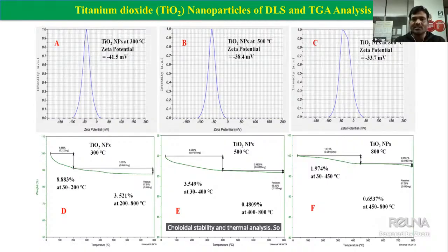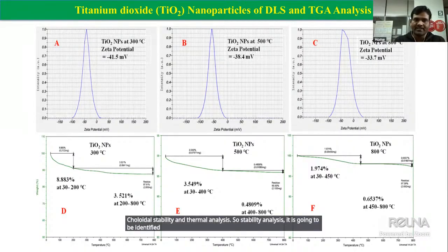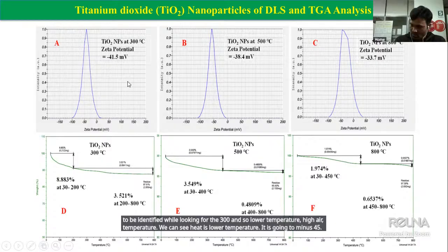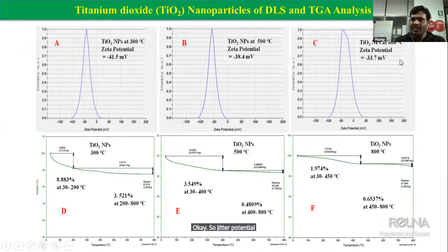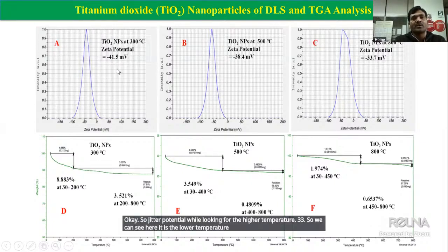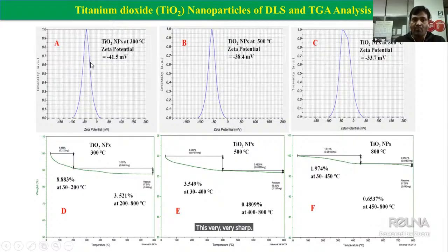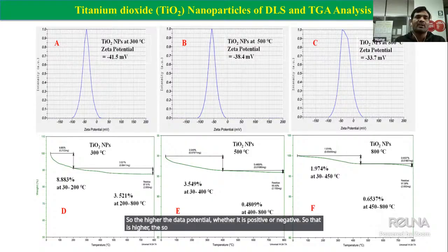So the stability analysis is identified for the lower temperature and the higher temperature samples. We can see here the lower temperature is minus 45, okay, the zeta potential. While the higher temperature is 33. So we can see the lower temperature sample has more stability of the nanomaterial. Why? Because it has a very sharp peak. The sharp peak indicates higher stability of the material. So that means the higher the zeta potential, whether positive or negative, the higher the stability of the material is confirmed.